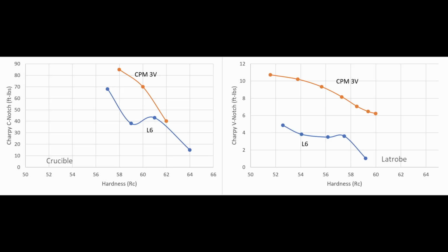So the numbers you'll see on these charts are much different than my test. You can't compare different toughness tests to each other. But these are two different companies, two different types of toughness tests, and they show L6 as being significantly less tough than 3V, where if it was testing in the 40 to 50 foot-pound range for my steel, it would test at least as well as 3V, but it is not what we saw from these two companies. So in a way, the L6 is meeting expectations if we look at old steel company data, but it's also not meeting expectations if we think about other nickel steels like 15 and 20.